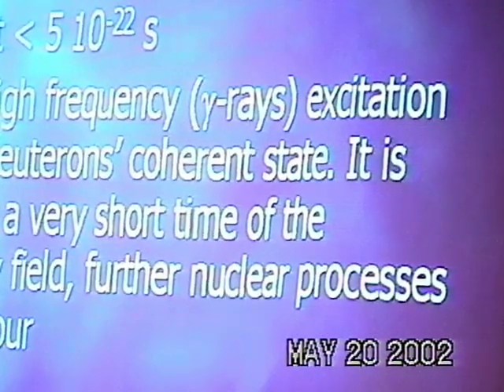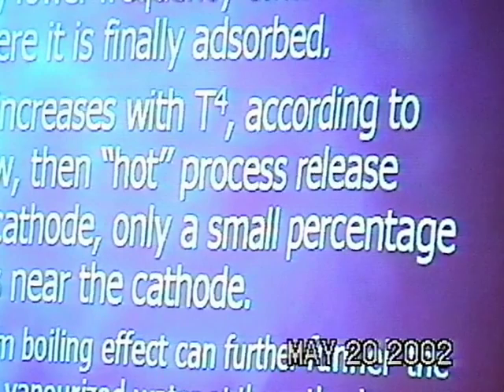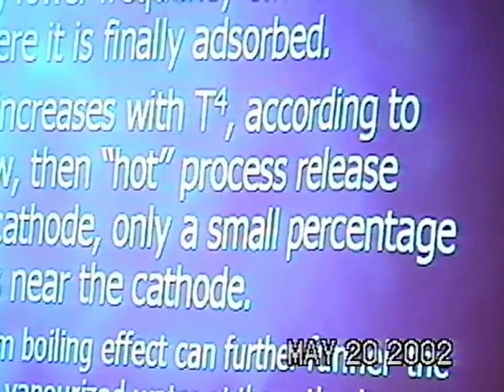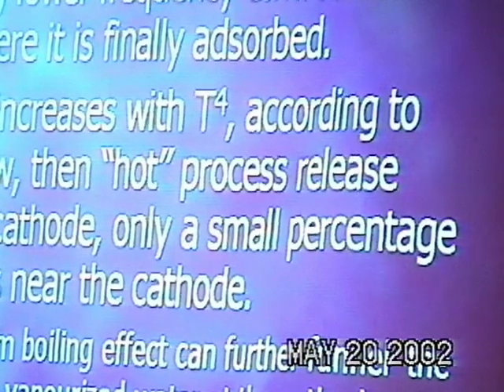After this time, if nothing happened, there is a small probability to happen. There is a very strong coupling between this energy, this gamma ray field, and the coherent field present in the matter, the field generated by the deuterons in the coherent state. At this point, the energy is thermalized in the lattice. The thermalization can happen through the emission of soft X-rays. The X-rays are due to the presence of d electrons, coherent, almost free electrons present in the lattice.